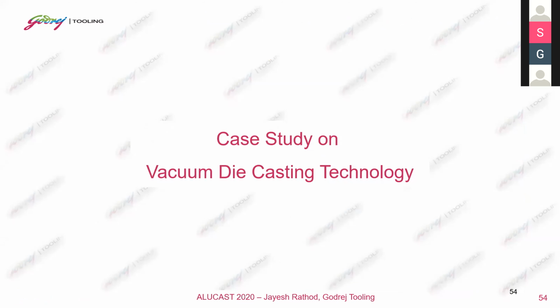And I would like to share a very interesting case study for the component and the die which has been developed by us. Originally, it was an LPDC part with very heavy and thick sections, owing to the constraints of LPDC as a process and also the product requirement with respect to load criteria. We have converted that into HPDC with 20% lesser weight, performing the same function and meeting all the quality and strength criteria. But because of the varied sections and the type of alloy used, it was quite challenging to fill the casting and achieve the level of porosity indicated by the customer.